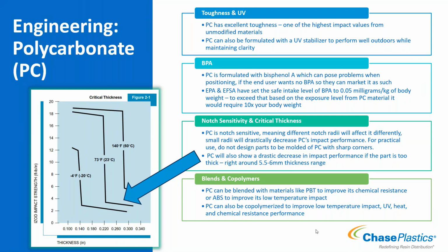Polycarbonate has excellent impact, but there are some nuances to that. Polycarbonate is also a very notch sensitive material, so if I use a different radii, a different thinner radii, it will affect how the performance will be for the polycarbonate. Meaning in a practical sense, if I design a part with really sharp corners, so there's almost no radius on it, it's not going to perform at the impact level you would expect out of a polycarbonate - you're going to drastically decrease its impact.